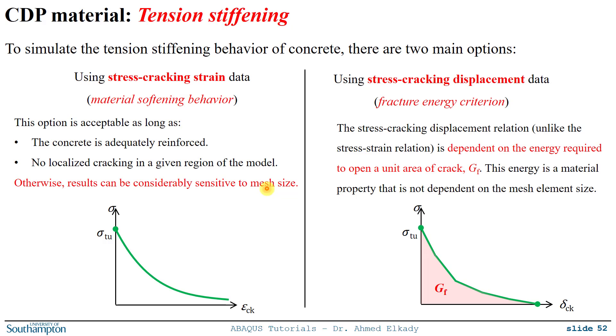In that case the curve is no longer an independent definition — it becomes dependent on mesh size, and you need to calibrate it through validation. This is a problematic aspect of using stress-strain data when you have mesh sensitivity issues: if you have a finer mesh the behavior will be different than with a coarser mesh, because how the strains localize differs between meshes. Instead, if your model has localized cracking appearing in part of the model, you can use the fracture energy criterion.